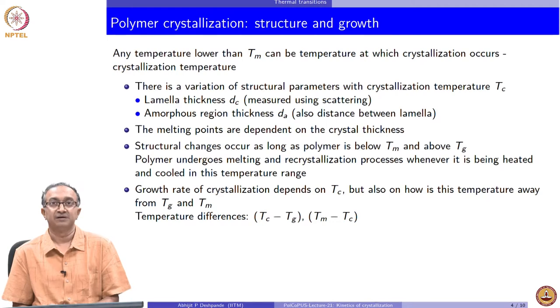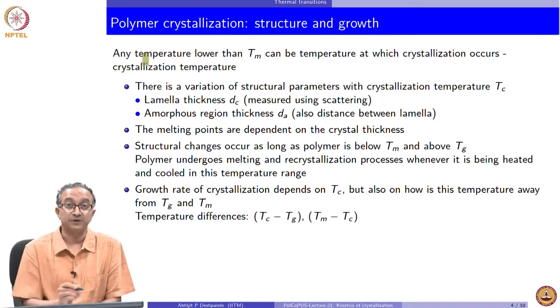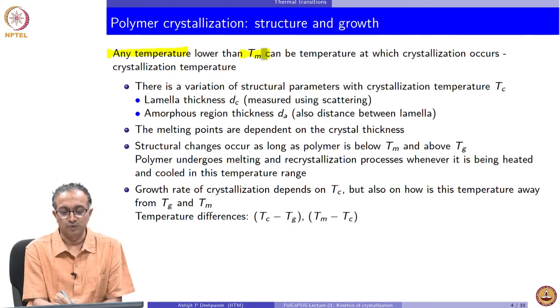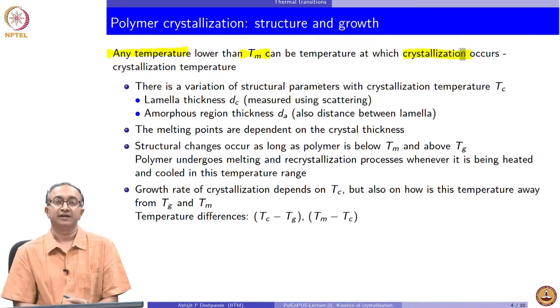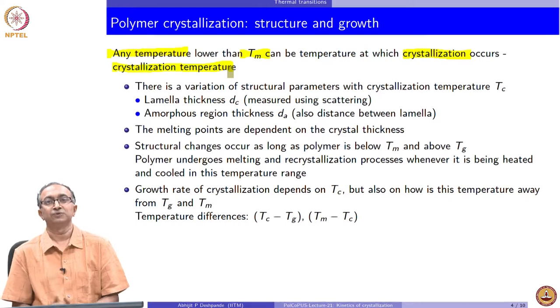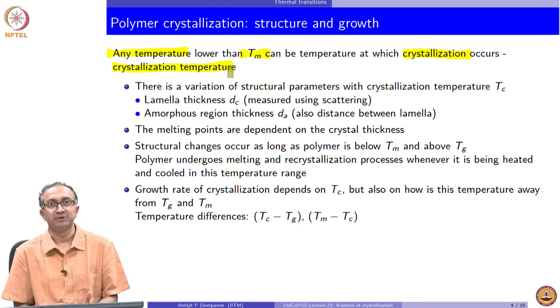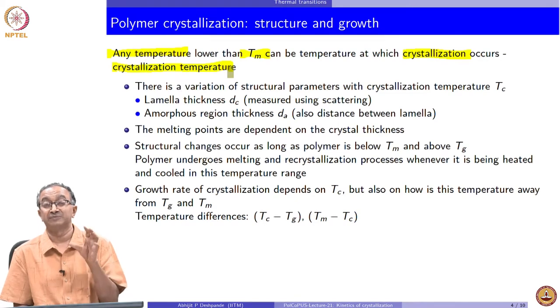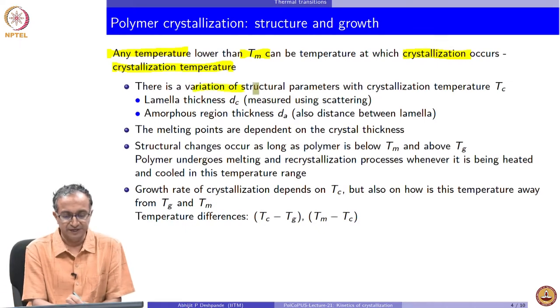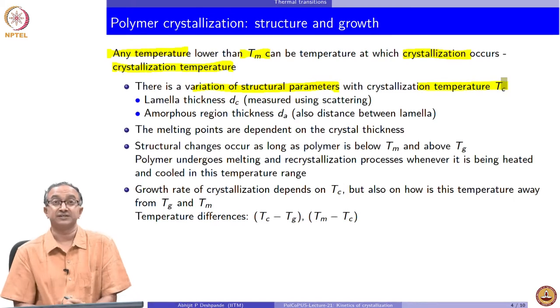Polymer crystallization — both the structure and growth — is possible when we look at what happens under a given condition. When the temperature is lower than the melt temperature, crystallization can happen, and we refer to that as the crystallization temperature. Above melting temperature, no crystallization is possible because the liquid state is favored due to lower Gibbs free energy. The only complication in polymers is that because of entanglements and macromolecular flexibility, 100% crystallinity cannot be obtained, and therefore we obtain folded crystals and spherulitic structures.